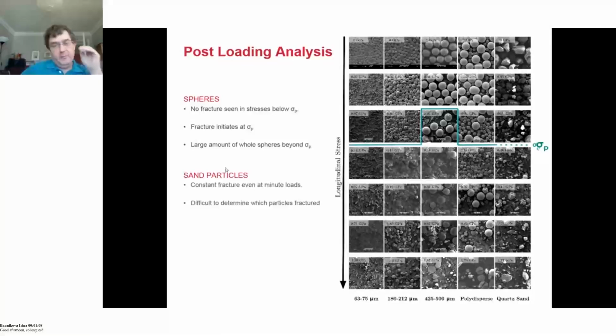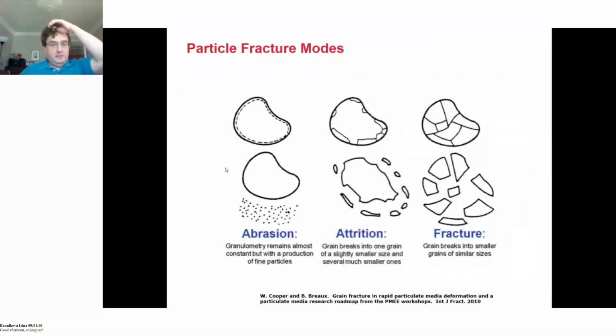So there are different ways of these particles fracturing. There's rubbing of particles against one another, which causes a small amount of dust to be produced. There is removing of larger amounts of material from the outside of the particle. And then finally, there is just particles breaking into fairly large chunks. So you can find again, there is a fracture strain rate dependence on the amount of each of these you see.